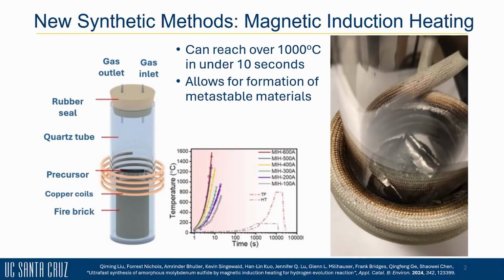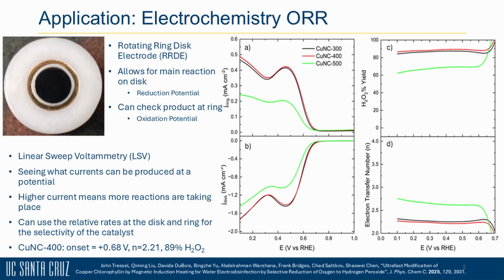To determine the electrocatalytic capabilities of the material, we used a rotating ring disc electrode to conduct linear sweep voltammetry. This allows us to vary the electrical potential at the disc electrode to determine the energy needed to generate products and to determine the selectivity of those products at the ring electrode. With this, our sample is able to reach nearly 90% pure hydrogen peroxide with a very minimal overpotential of about 20 millivolts in acidic, neutral, and alkaline electrolytes.